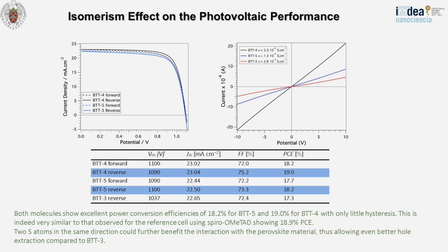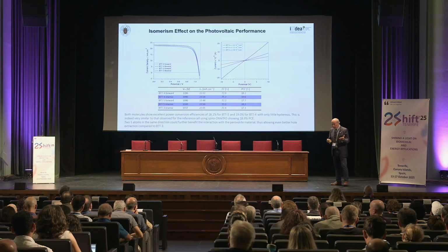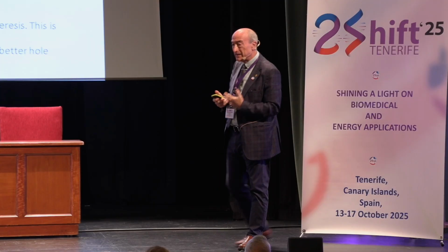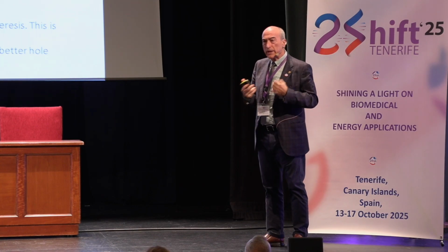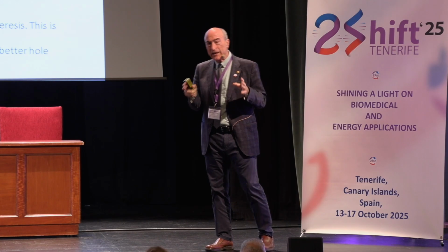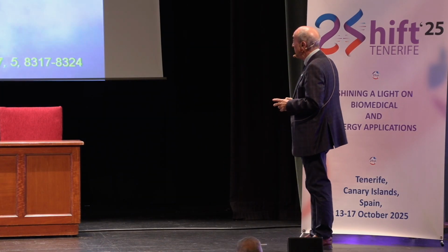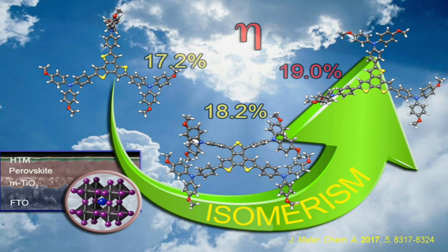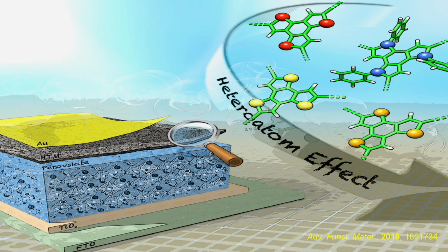In agreement with this, the best value was obtained for BTT4 because the electrical conductivity resulted to be higher. So the idea was to synthesize molecules and see by design if we could improve some of the properties. And the conclusion was that isomerism also plays a role, because when you have the sulfur atoms at different positions in the central core, you increase from 17, 18 to 19. Another possibility was to modify the nature of the heteroatom inside.